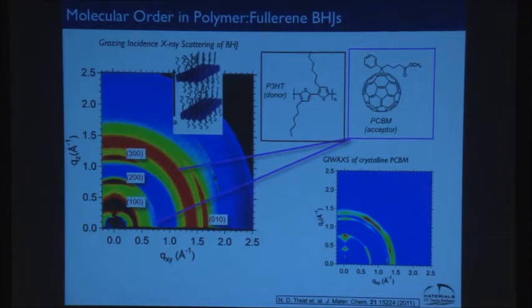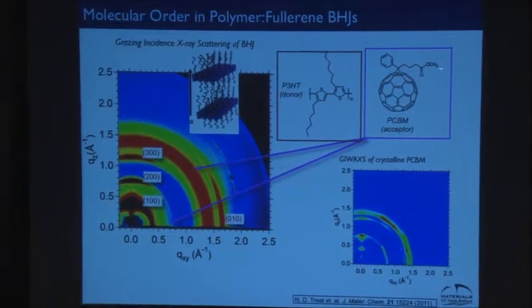And so what happens is in those TEM images, you can imagine the polymer is there, and it does have domains that are highly ordered, but the fullerene that's in between is just glassy, right? And that's easy to see. It's kind of like a ball. You can think about the fullerene that way. And so you see significant disorder in this phase for sure, and actually a bit of disorder in the polymer as well. It's not like a piece of silicon.